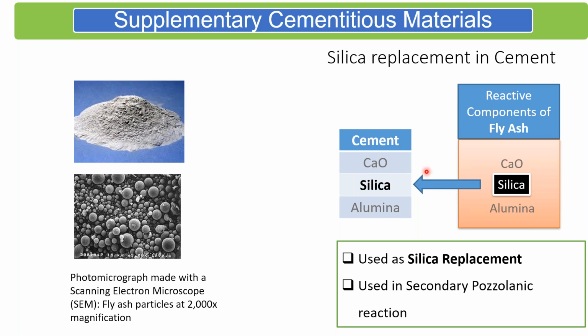And so when I replace cement with fly ash, essentially what I'm doing is a silica replacement. I'm replacing the silica that's coming from cement with the silica that's coming from the fly ash. But in the process, of course, I deplete the lime, because cement is lime rich, whereas fly ash has a very low quantity of lime.